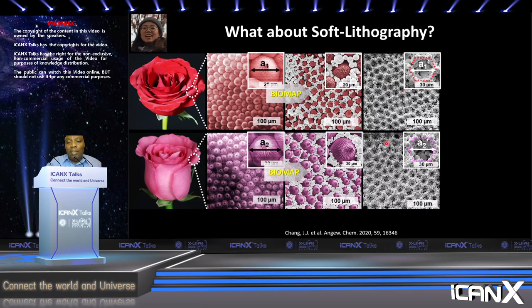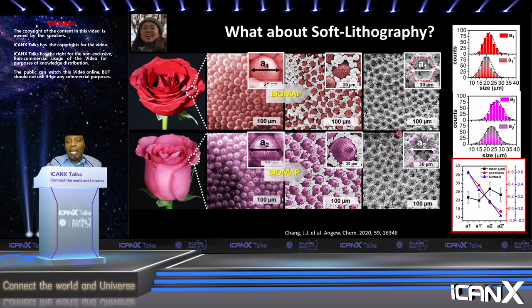And we can get the structures replicated, and we measure the average diameter of each of these features, and we see that there's a slight difference between the rose flowers, the A1 and the A2. There's a small difference, and we see the same difference in the structures that we replicate. So we can differentiate between these two flowers based on this metal-based soft lithography.